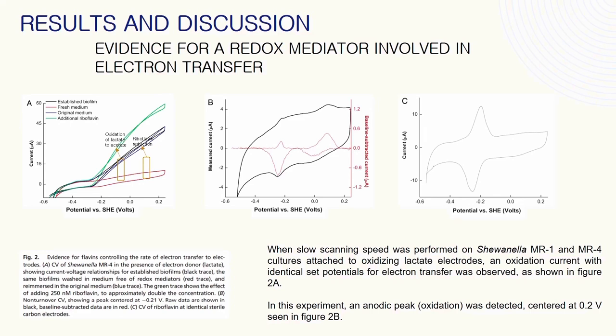These conditions are designed to detect redox species at slow scanning speeds, without interference from the current resulting from lactate oxidation. In this experiment, an anodic oxidation peak was detected, centered at 0.2 volts, seen in Figure 2b. These observations are consistent with the peaks observed when sterile electrodes are incubated with riboflavin.